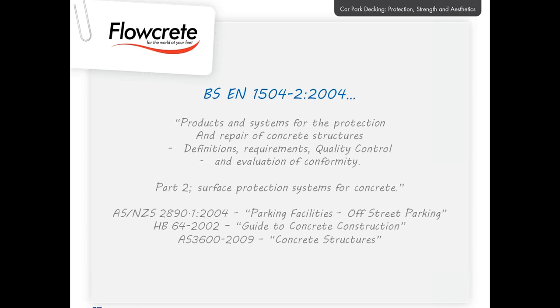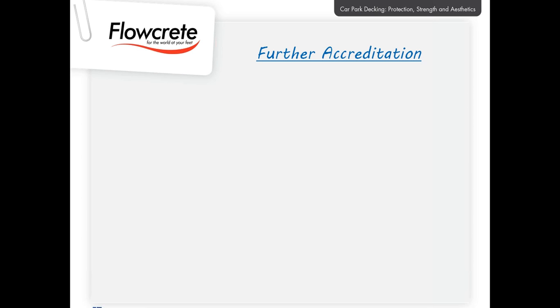Heavy-duty polyurethane or MMA coatings systems are best suited to ramps, as they offer all the materials' inherent crack bridging and wear-resistant properties. The materials can also be applied at greater thicknesses and have the ability to be broadcast with stronger aggregates, including aluminium oxide, in order to ensure a strong, textured and anti-slip finish. Heavy-duty polyurethanes and MMA systems are also elastomeric and provide good crack bridging properties.